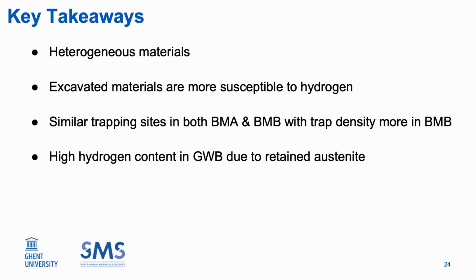So the key takeaways from this study are that both the pipeline steel versions have a very heterogeneous microstructure. The excavated materials are more prone to hydrogen embrittlement because of their high hydrogen uptake and the brittle fracture that they have. Then, BMB has a higher trapping density than BMA, and they have similar trap types, shown by the desorption peaks. And then, the presence of retained austenite can contribute to the high hydrogen uptake by GWB.